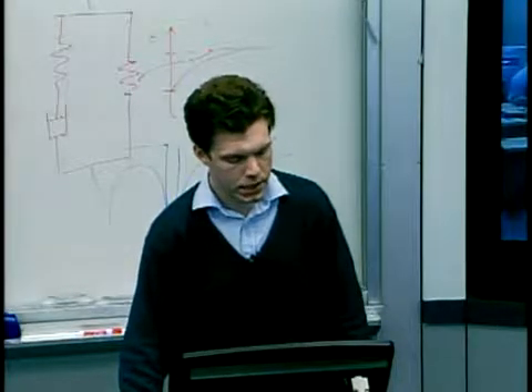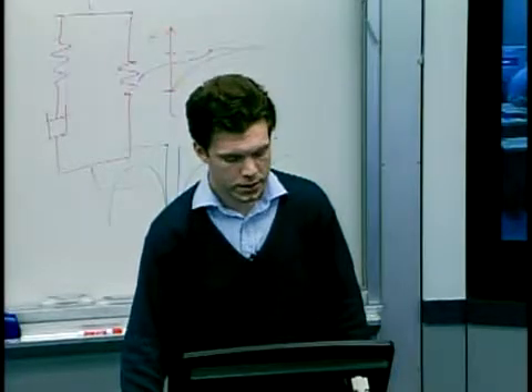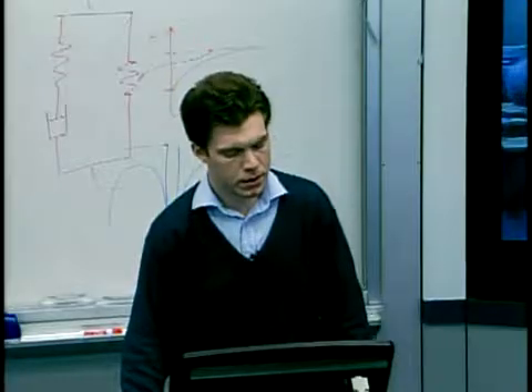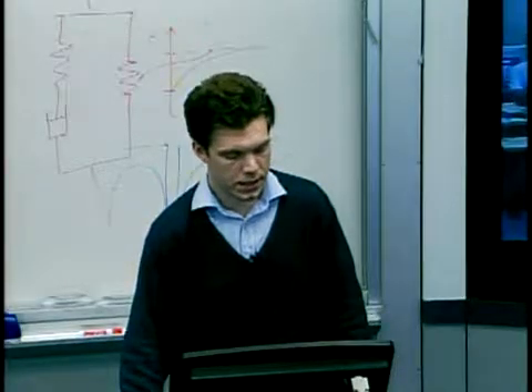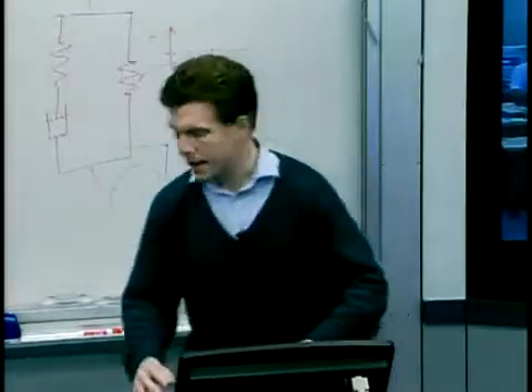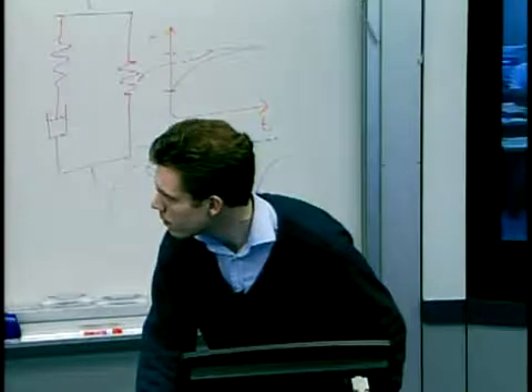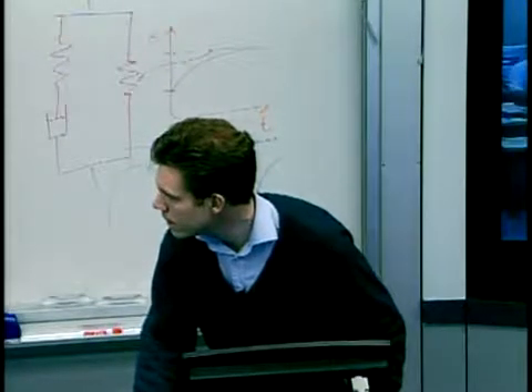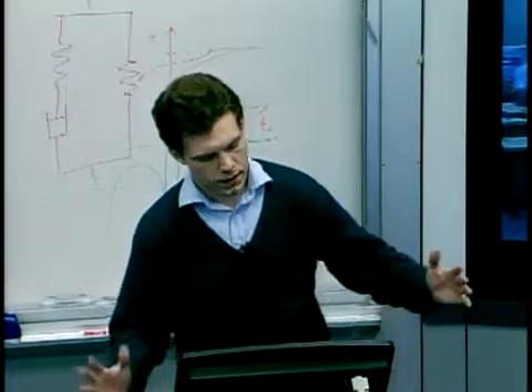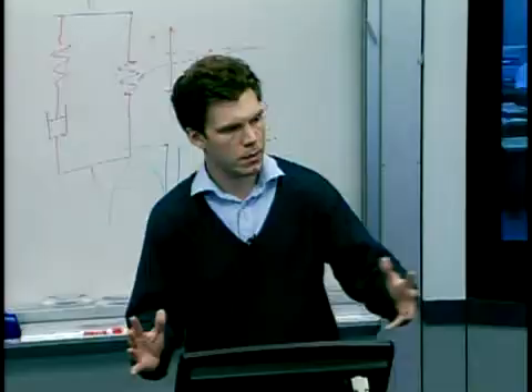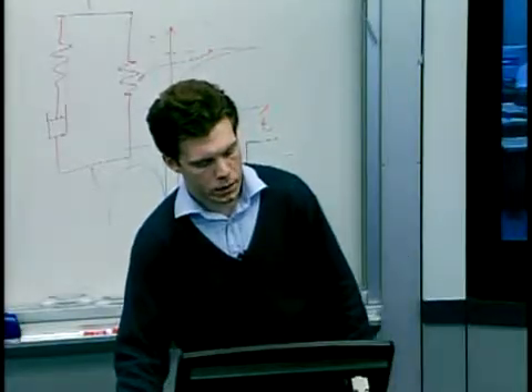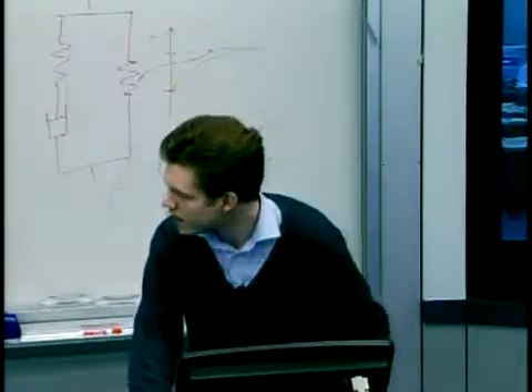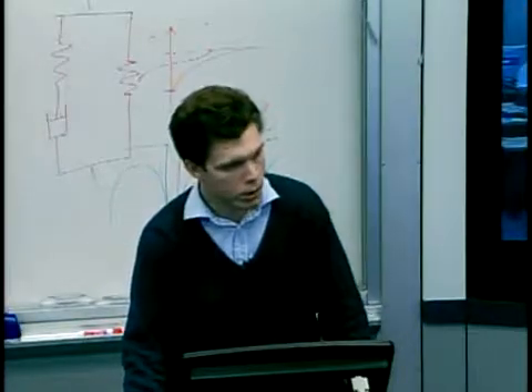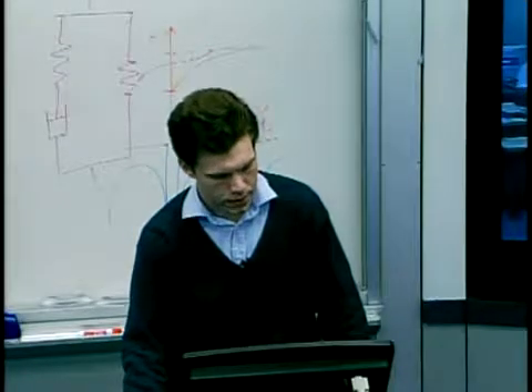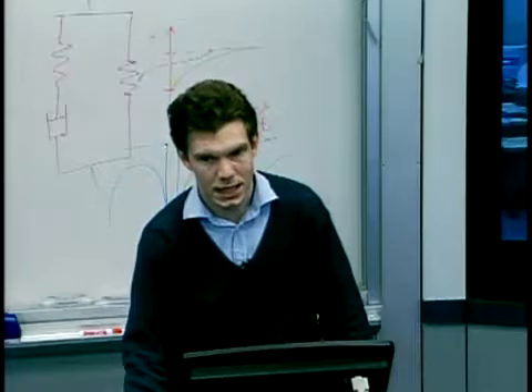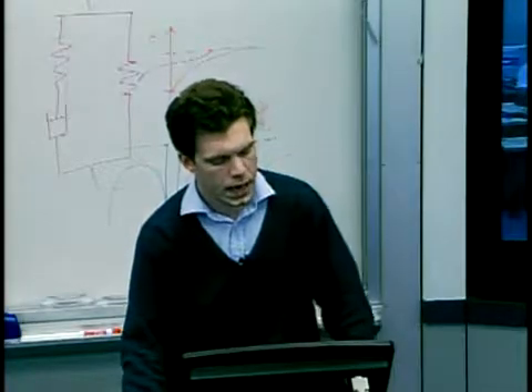This is an SEM picture of a PMMA component that has been embossed with a hexagonal post. This was made from silicon, in fact. If you imagine the substrate being mostly on this side of the feature, cooled under load, the polymer having at least 10 times the thermal expansion coefficient of silicon has pushed itself against the sides of the features, and when we demold, we get these really substantial ridges. I think this was embossed at 130 degrees C, so 20 degrees above glass transition.